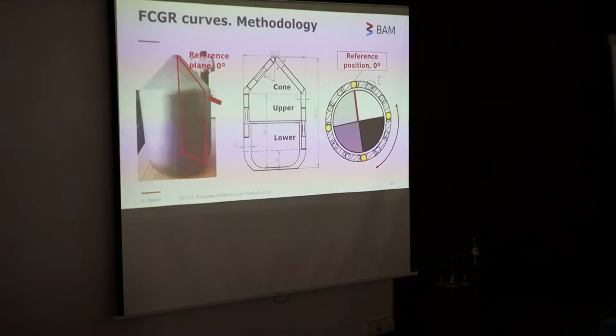In any case, according to the fatigue crack growth rate curves, we are defining a reference plane, which coincides with this one, and we are trying to characterize different positions along the circumferential direction in order to see if there are different responses depending on the position. And you can see here the three regions that I mentioned before: the lower part of the cylindrical part, which has 15 millimeters thickness, the upper part, which is 11 millimeters thickness, and the cone part, which has 45 degrees of tilt regarding the building direction.